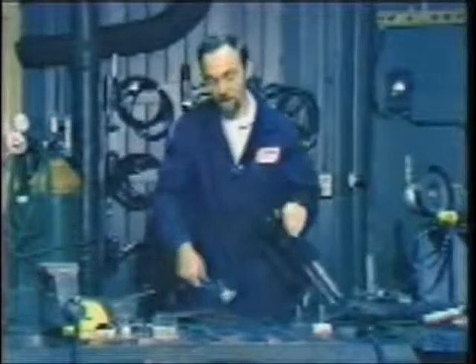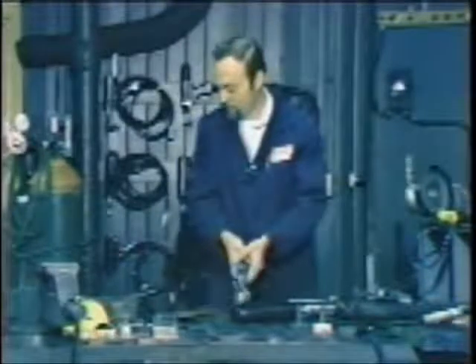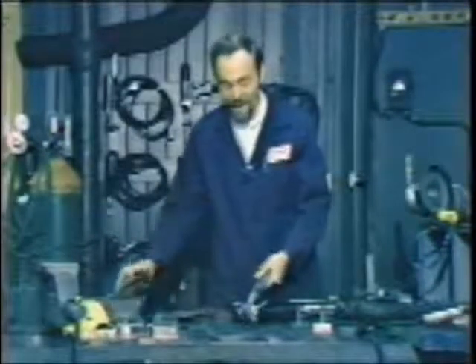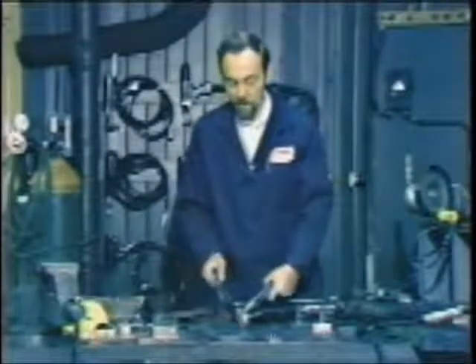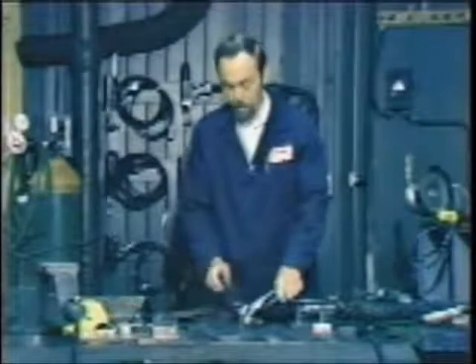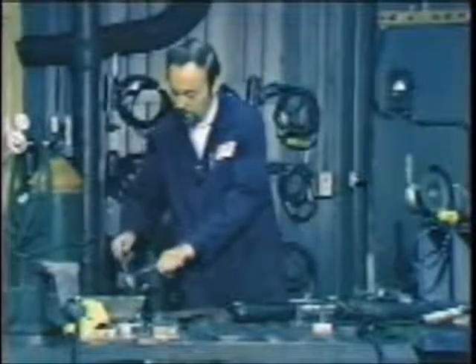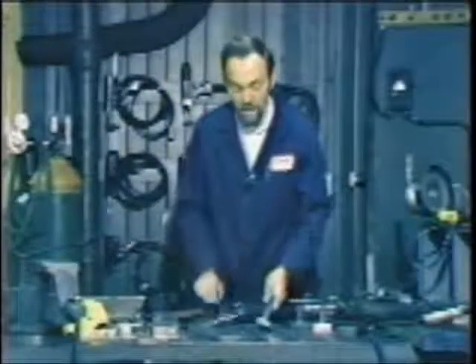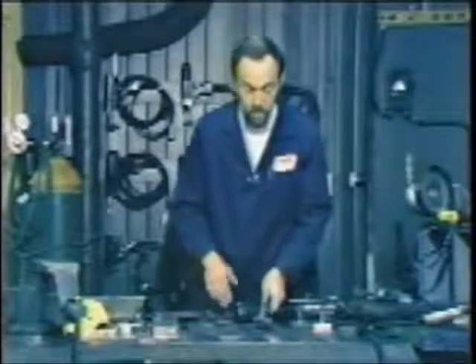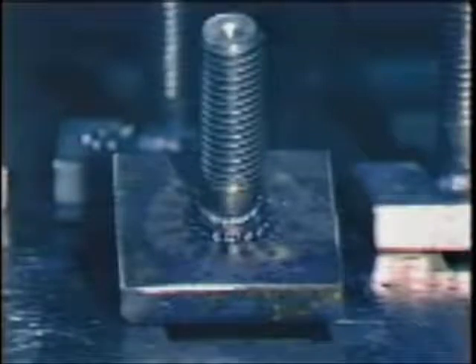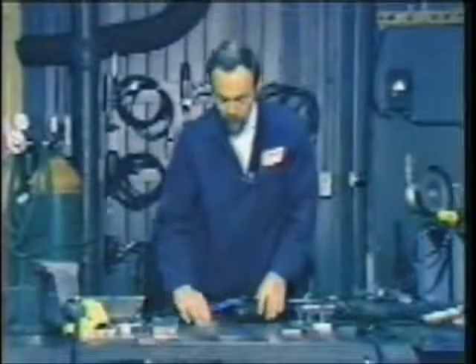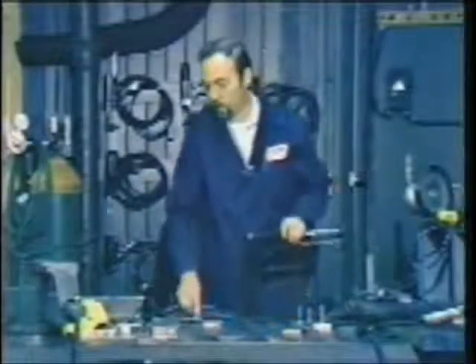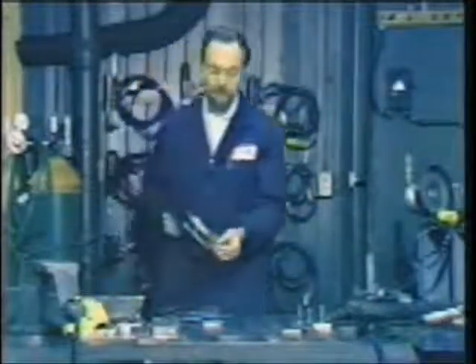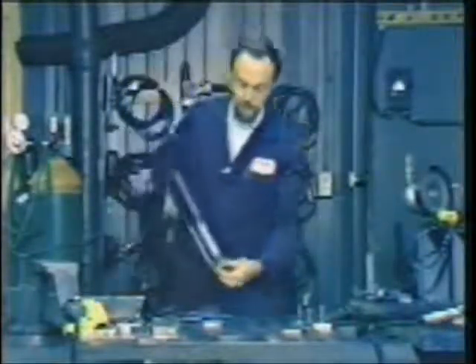We'll take that out. The weld berries and ferrule break off easier after it's cooled slightly. You have a glazing in there between the fillet metal and the ceramic ferrule. If you tried to break that off immediately, the ferrule wouldn't have chilled, but we've got a nice bright fillet appearance there. In making the same weld onto mill scale, you'll get more metal expelled in the form of weld berries and slag.